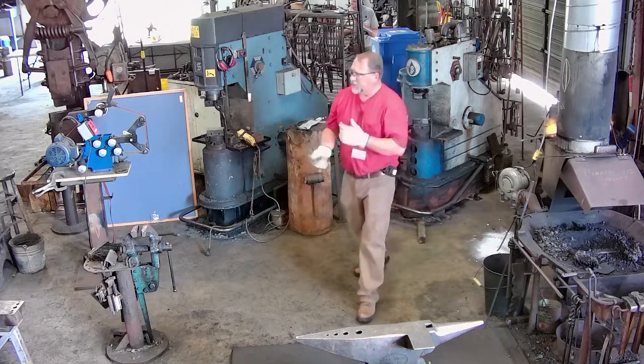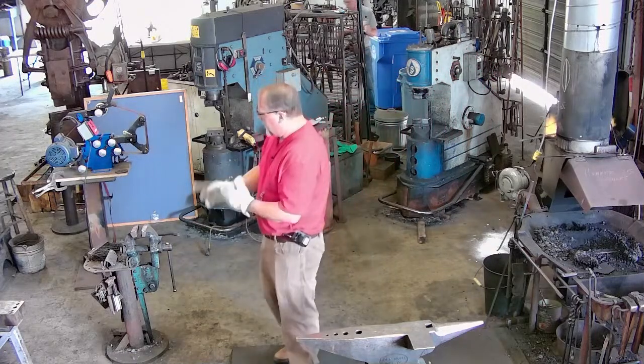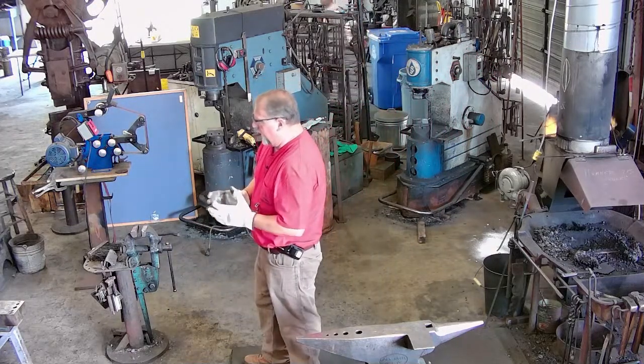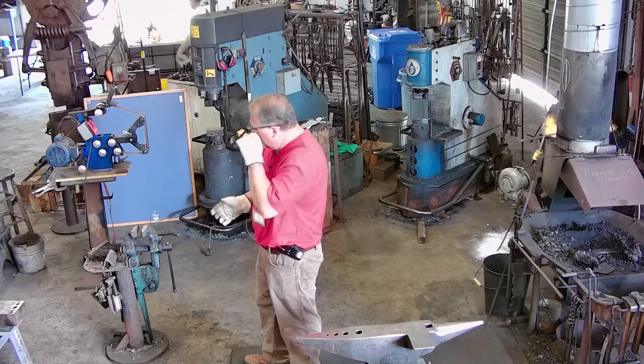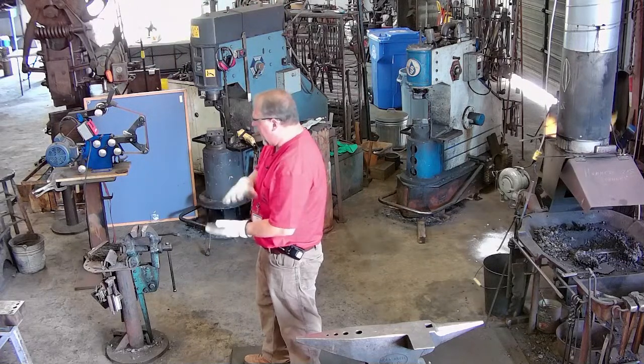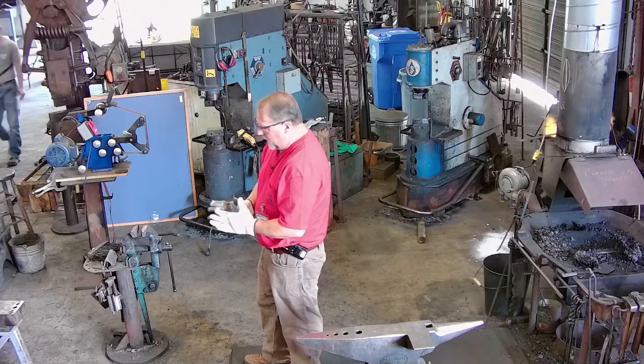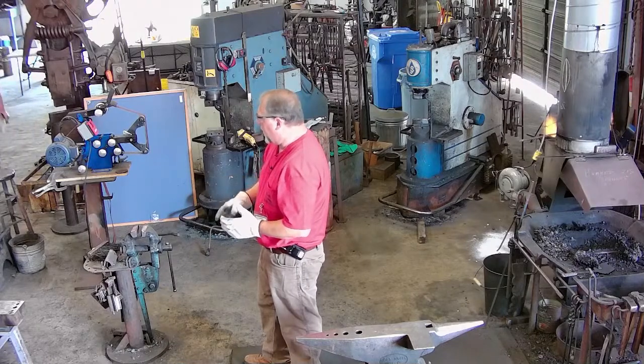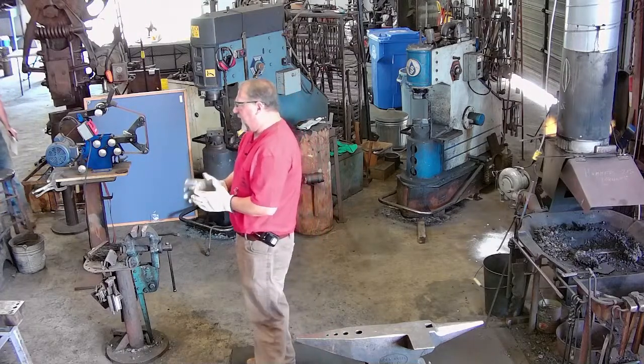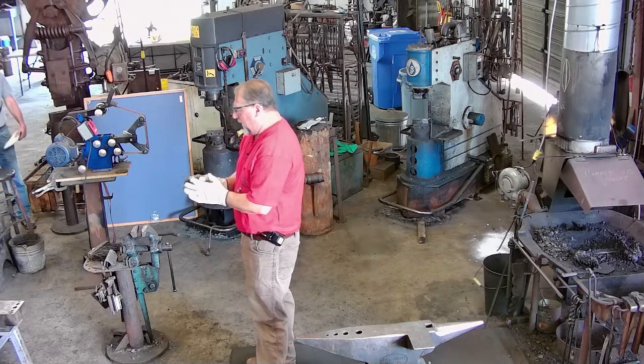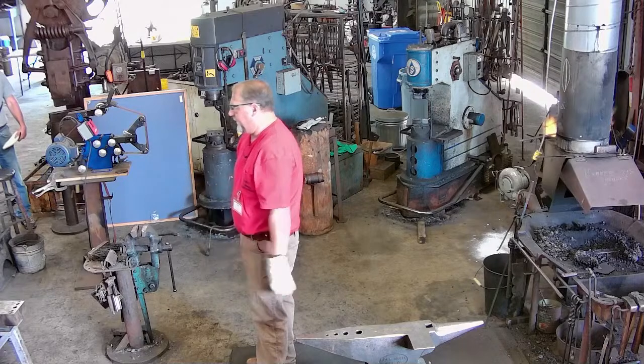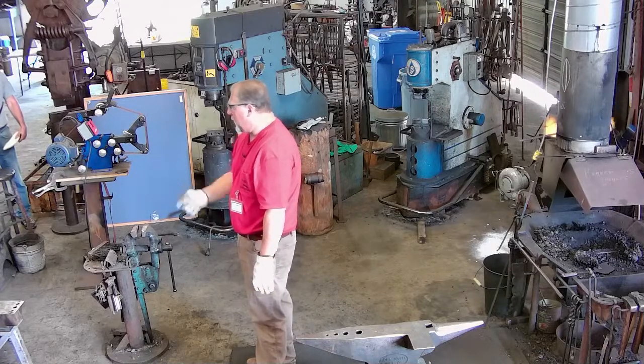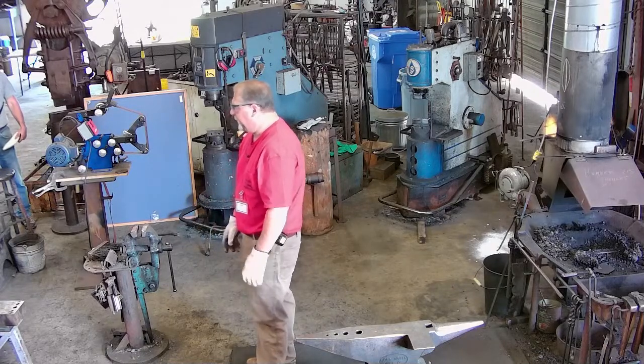So if you notice, I'm continuously rotating my billet as I do it. The intent is to try to keep it as square as I can while still spreading out the edge grain. And the reason I keep rotating it is, if you only hammer on the edge grain, your billet will have a tendency to either bow out or deform on those edges, and it bites you later on when you're trying to forge a blade out of it.